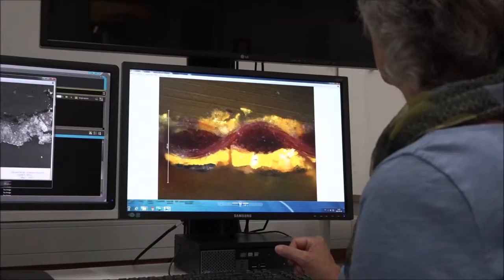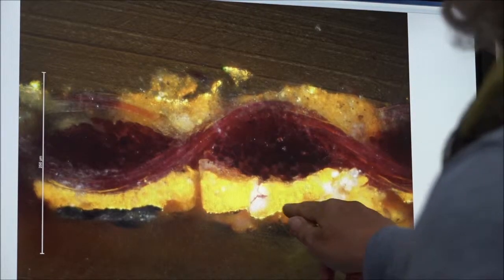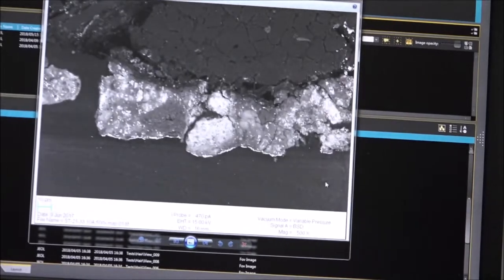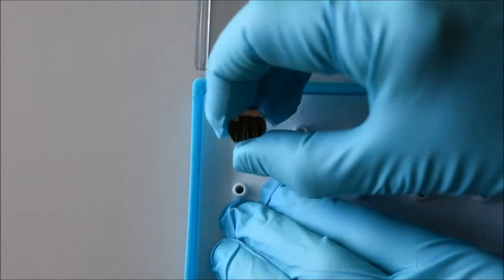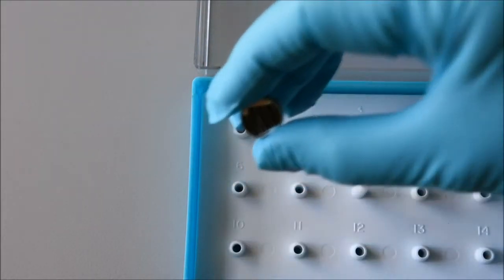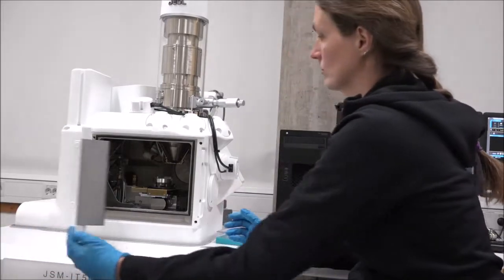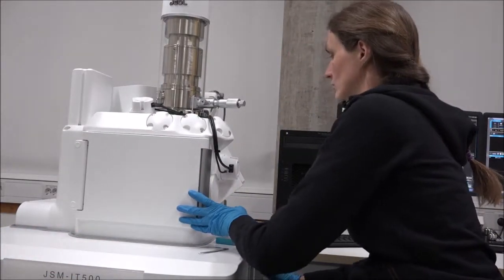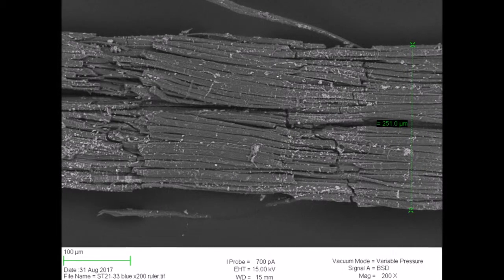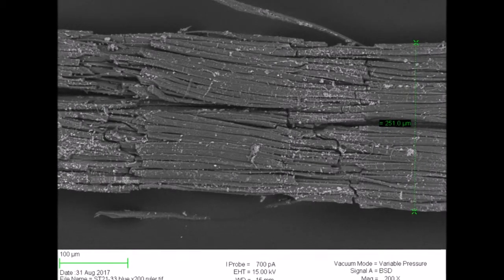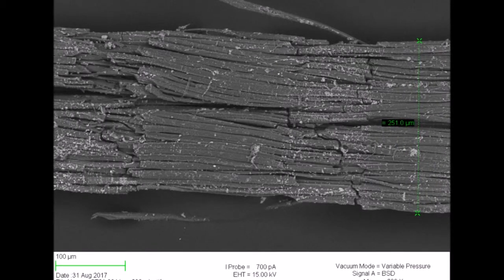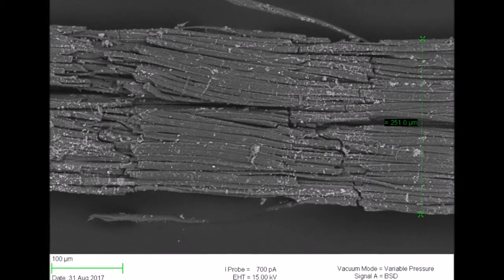We also investigated the cast paint samples in a scanning electron microscope to look at metal content and could determine gold, silver, copper and lead. It was also interesting to take a closer look at the weft threads from the Streltsy colour in the scanning electron microscope. A specimen stub with weft threads is mounted. Here is one of the blue weft threads. The fibres are in poor condition and have many breaks.